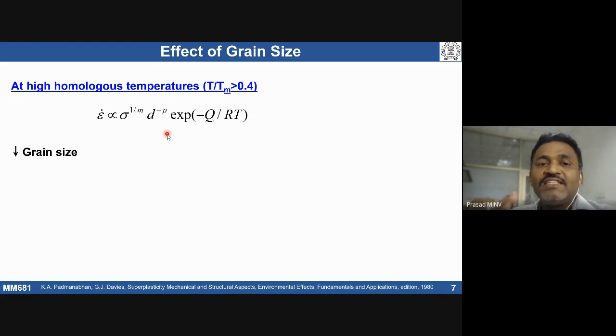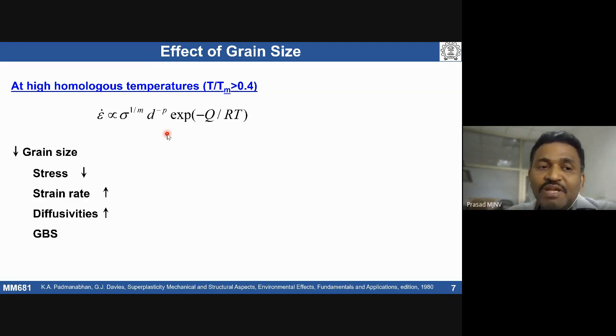If you have a finer grain size, more grain boundary area, so grain boundary mediated deformations can happen, like grain boundary sliding can take place very easily. A higher amount of grain boundary sliding can be there if you have a finer grain size. So these are the beneficial things we see when you refine a grain size. Because of these activities, that can lead to large uniform elongations in fine grain size materials. However, one of the major issues if you refine a grain size,